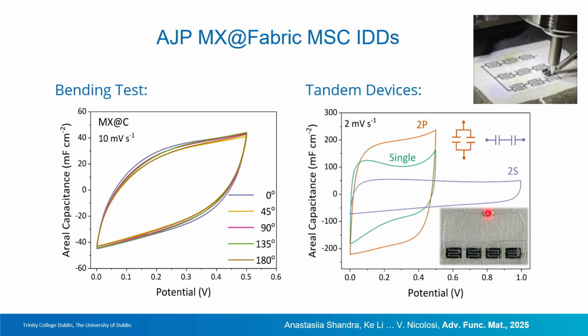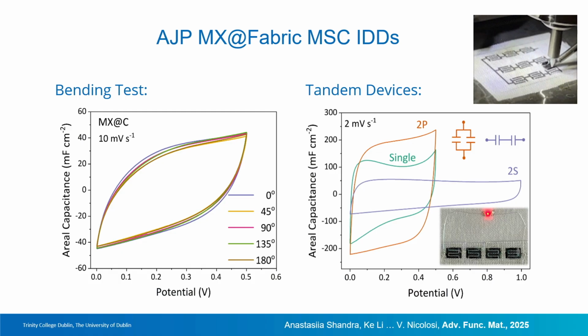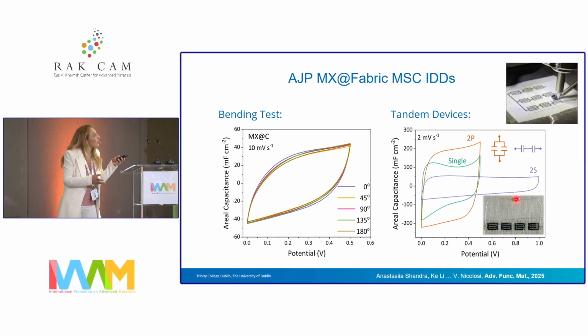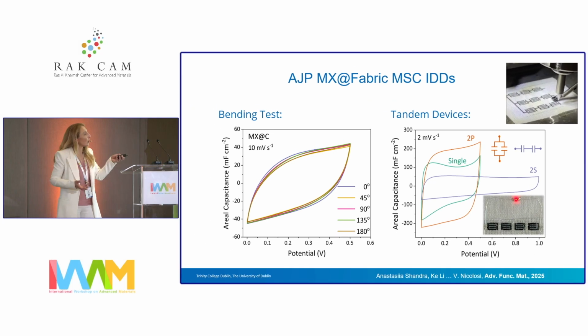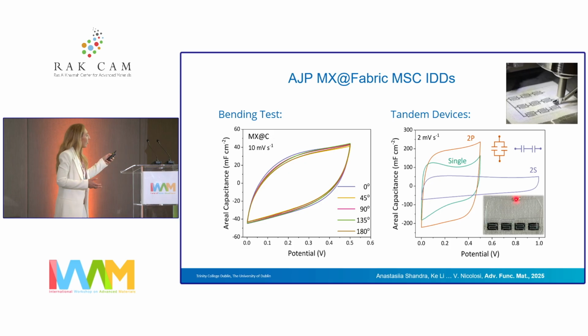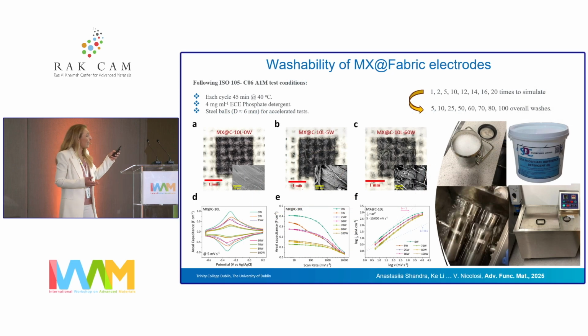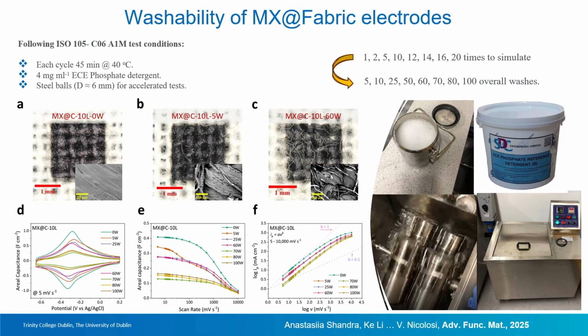Being all printed, you have the additive manufacturing freedom, which means that you can make asymmetric devices as well as symmetric devices. And by going to asymmetric, you end up increasing the potential window that you can get. Last but not least, we did some washability tests, ISO certified, and we saw that you can push hundreds of washes and the electrochemical stability of the device is still retained. You have some decay from the first 5 cycles of washing, and then it stabilizes and the performance is retained.